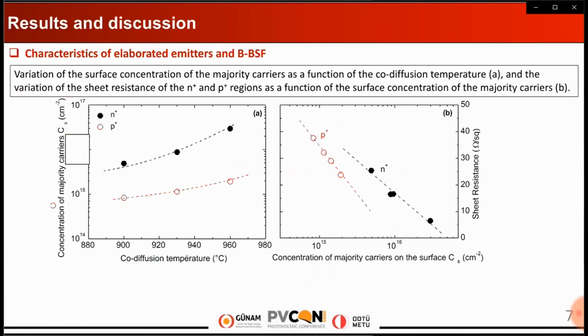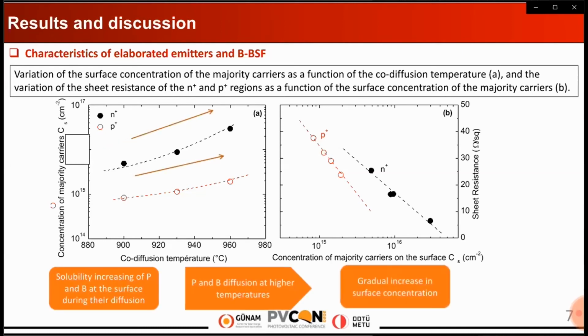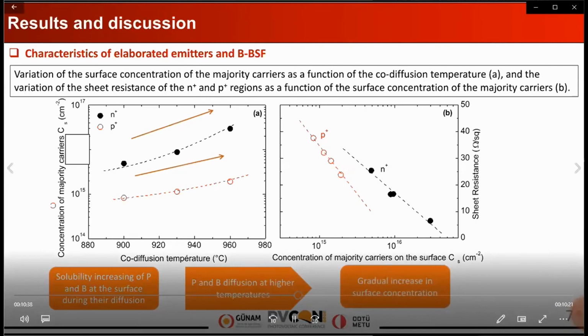So, we present in figure A here, on the left, the surface concentration of the majority charge carriers obtained by Hall effect as a function of the co-diffusion temperatures of phosphorus and boron. It is clear that the increase in diffusion temperature of dopants causes a gradual increment of the surface concentration in the N plus and P plus regions.